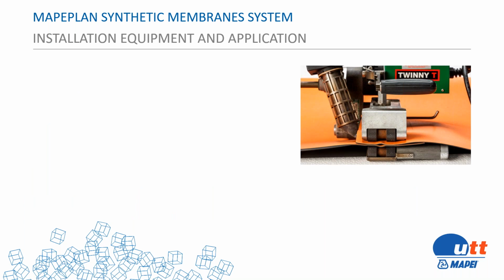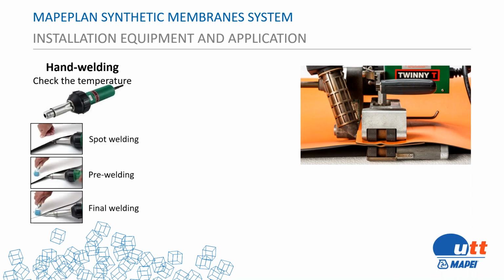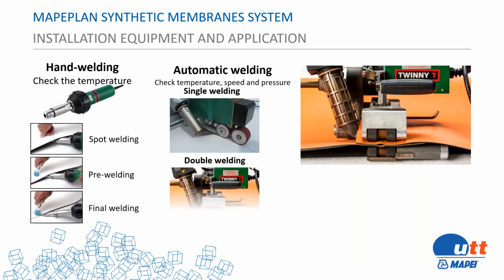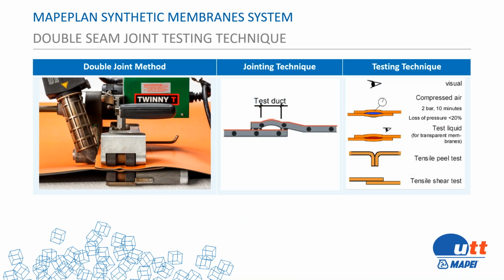As I mentioned, the most important part of the PVC system, or why the PVC system is recommended when it comes to tunnel construction, is the welded overlap. So we're using a hand welding machine to weld the overlap, or an automatic welding machine. The automatic welding machine can give us a single weld or double weld. Most of the time, most of the standards ask for a double welding overlap. Double welding overlap means we have two seams, one on the right and one on the left, and in between we have an air channel, an open channel, and we're using this channel for testing purposes.